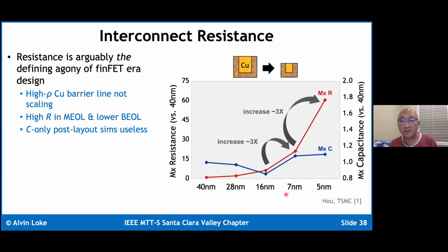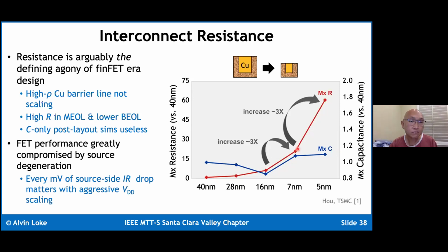Very simply, if you look at, for instance, some data that TSMC has shown, going from node to node, you can see that the capacitance has gotten a little bit worse, but it hasn't taken off exponentially like it has for the advanced FinFET nodes. Because the series resistance is so bad, the FET performance, especially when you're down to very aggressive supply scaling, is going to be significantly compromised by source degeneration or access resistance on your transistor.